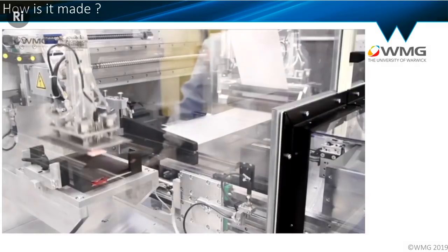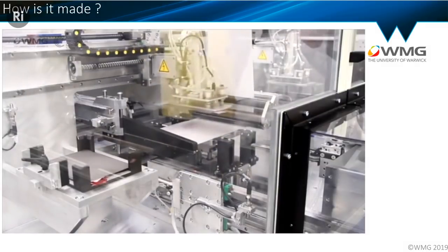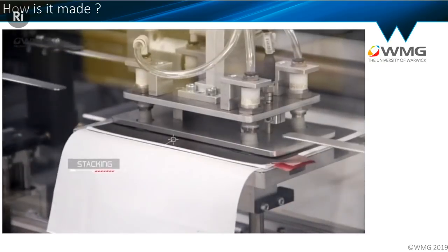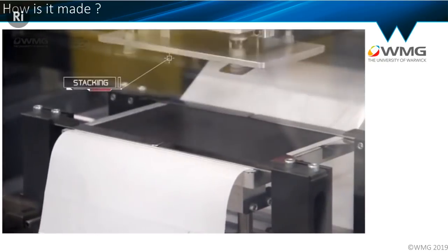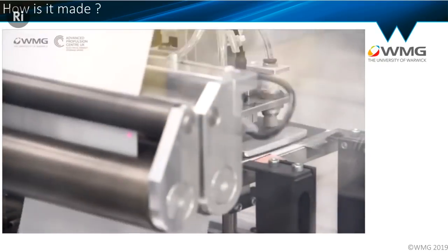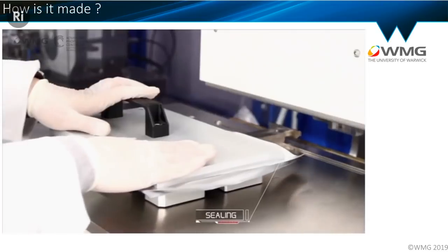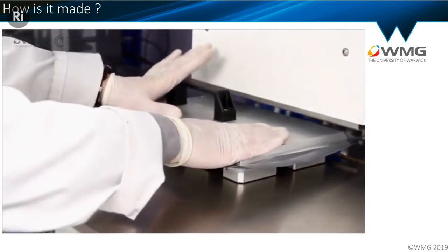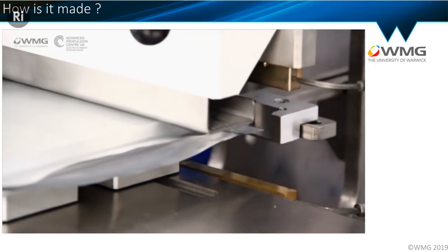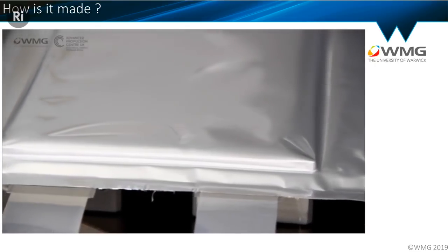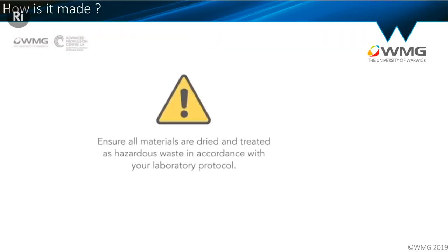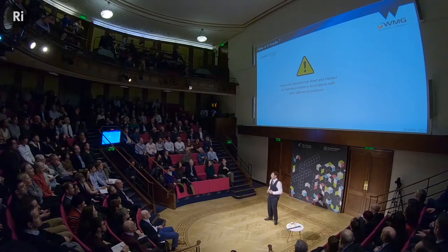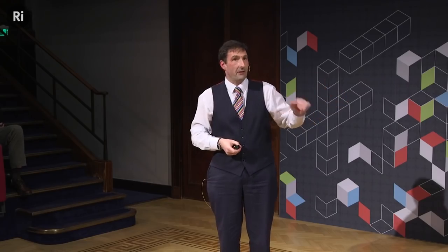the materials. We use a robot to assemble them because the alignment of those anode and cathode foils is absolutely critical to the quality of the battery. It's one of the things that can cause it to fail early in its life. We then seal it into a material which is actually very similar to a coffee bag. Coffee bags resist moisture for about 3 months. That material resists moisture for about 15 years. And having done that with the electrolyte, we then take the thing off, ready to form.